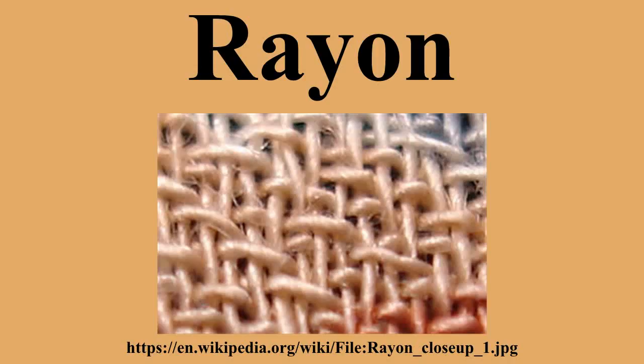The aged white crumb is mixed with carbon disulfide in a process known as xanthation. The aged alkali cellulose crumbs are placed in vats and allowed to react with carbon disulfide under controlled temperature to form cellulose xanthate. Xanthation changes the chemical makeup of the cellulose mixture and the resulting product is now called yellow crumb. The yellow crumb is dissolved in a caustic solution to form viscose. The viscose is then set to stand for a period of time, allowing it to ripen.